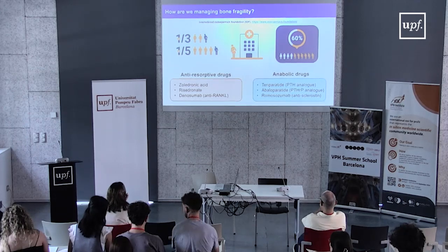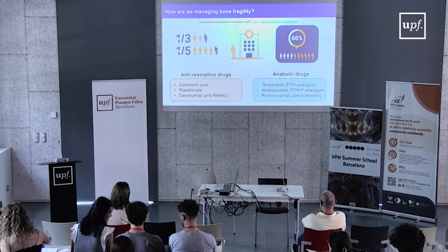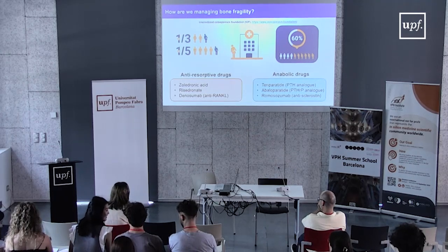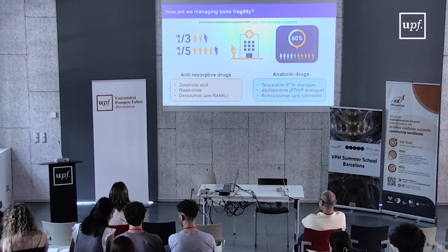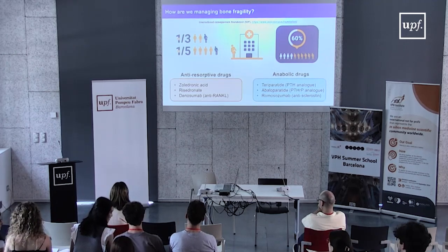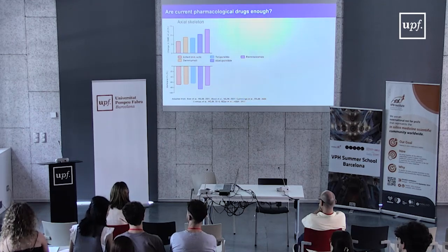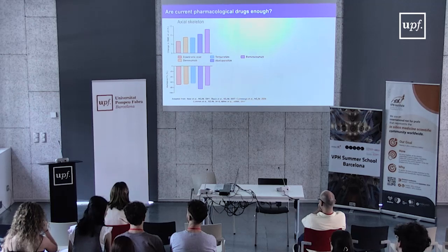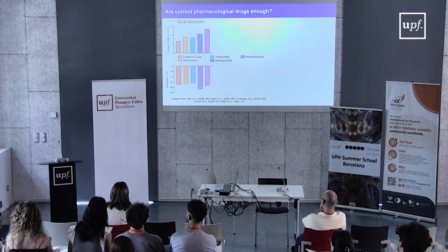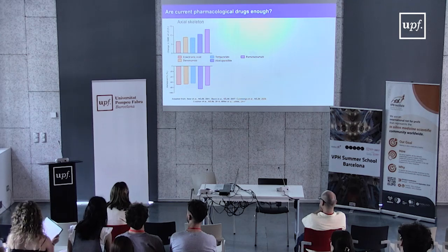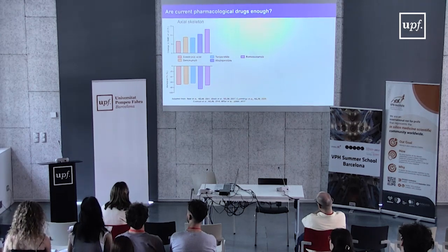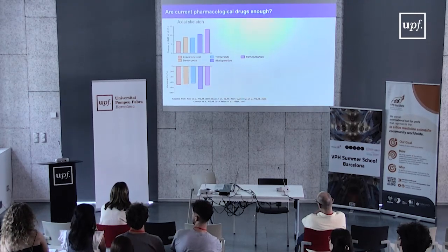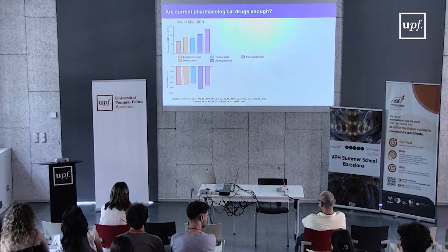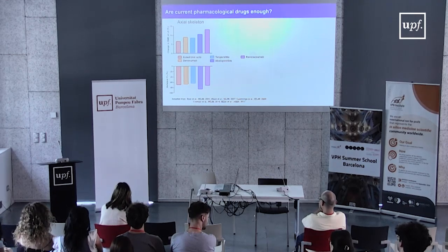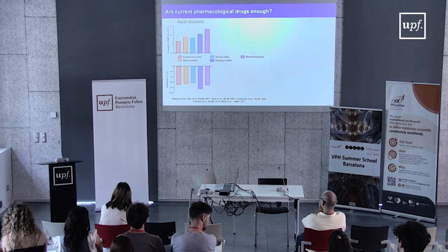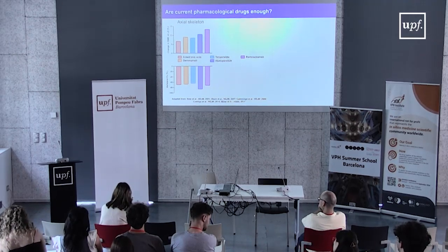But both strategies, anti-resorptive drugs and anabolic, will only target the quantity of bone material. And they target only the quantity of bone material because clinically, we only assess this parameter through DEXA scan, at least non-invasively. And this is really a problem, actually, in the care of our osteoporotic patients, because if you look at the axial skeleton, so the lumbar spine, bone mineral density will be increased with the newest molecule by almost 12%, and this will lead to a reduction of almost 70% of fracture. So in the lumbar spine and axial skeleton, measuring the quantity of bone by DEXA is effective and it's working quite well, we can say.